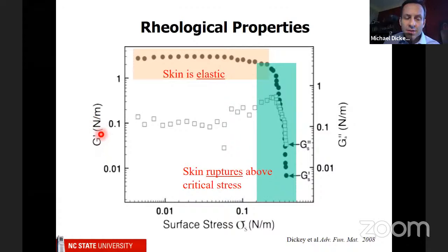So from these measurements, we get this information. This is the elastic modulus. Actually, it's the elastic surface modulus. So it's newtons per meter, and it's plotted as a function of surface stress. So if you think about the stress like this, when you stretch something, at least in the case of a piece of rubber, there's the modulus, or you might think of it like a spring constant, like Hooke's law. And that constant is what's being plotted right here.